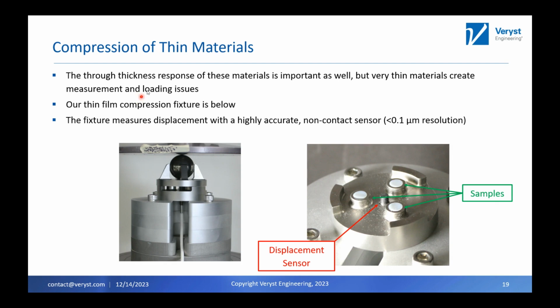Actually, we're going to start over on the right. The right shows the actual fixture down here at the base, and then the samples. We've created 3 discs of material, again 100 microns thick. I think these ones are 6.3 millimeters in diameter. We put those 3 on these 3 pedestals. Then coming up from underneath, we have this round thing here, which is actually a non-contact displacement sensor.